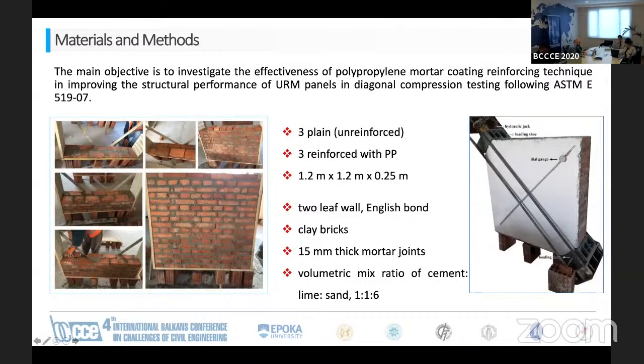The diagonal compression test is done as in the figure to the right, where we have a hydraulic jack that is exerting the pressure. We have the loading shoe on both edges of the main diagonal where it is compressed, and we have dial gauges that measure deformation on both sides of the wall. The wall has been constructed using two-leaf English bond, using clay bricks, and the mortar joint is 15 millimeter thick. These walls have been built by an experienced mason so that we can somehow have a similar construction typology for unreinforced masonry buildings that are in Albania or elsewhere. The volumetric mix ratio of cement, lime, and sand is 1:1:6.